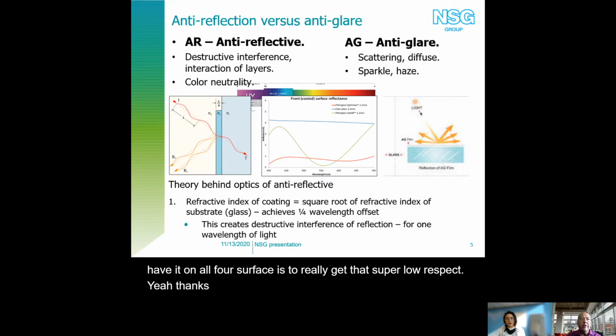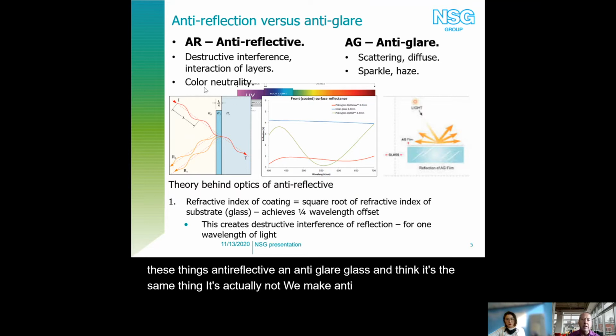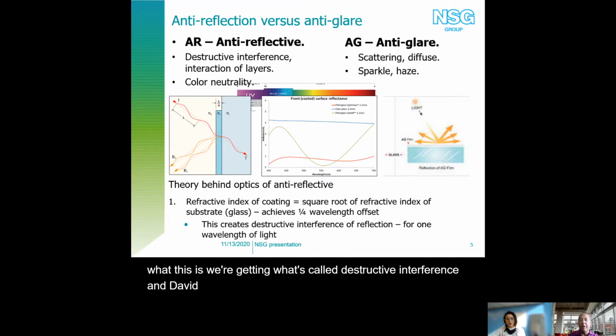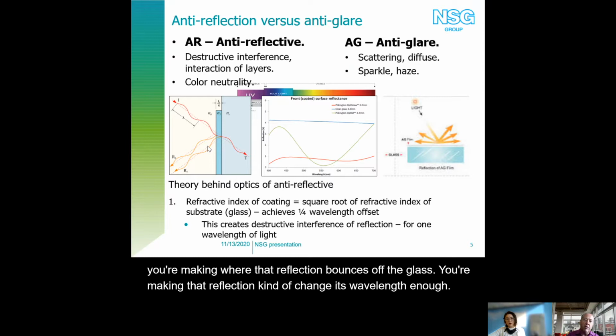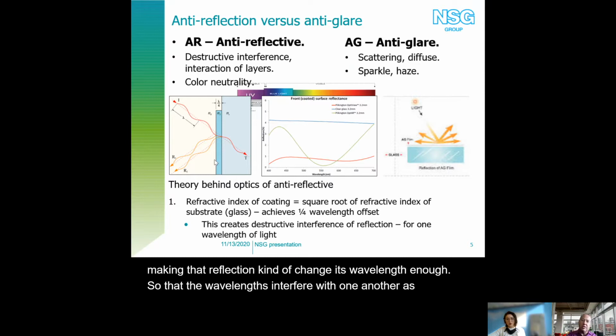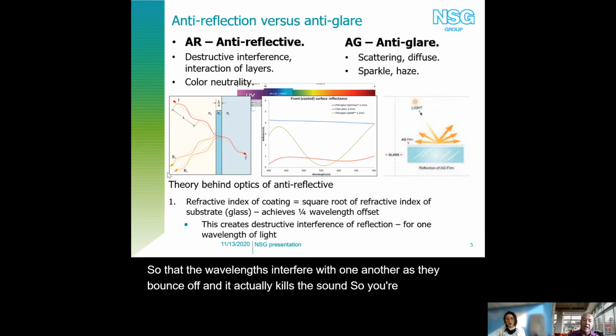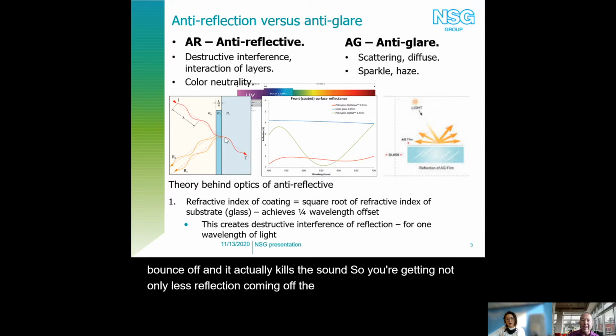Yeah, thanks, Kayla. A lot of people intermix anti-reflective and anti-glare glass and think it's the same thing. It's actually not. We make anti-reflective glass, and what we're getting is what's called destructive interference. David Strickler and the coating guys will give you a lot better information on this than I will. But what you're doing is taking all those multiple layers of coating that we make, and where that reflection bounces off the glass, you're changing its phase enough so that the waves interfere with one another as they bounce off, and it actually cancels the reflection. So you're getting not only less reflection coming off the glass, you're actually boosting the light transmission that goes through the glass.